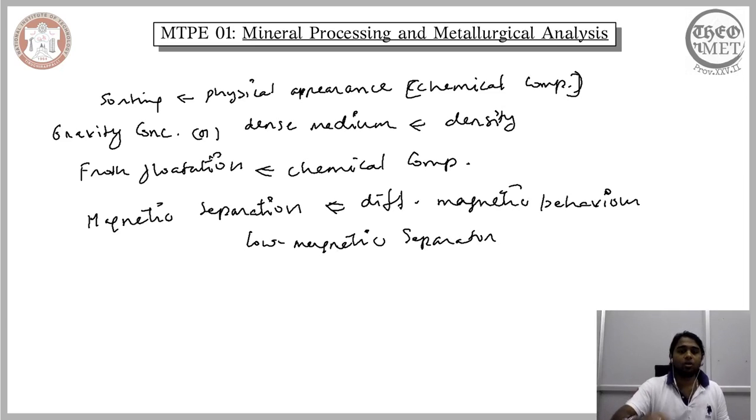And therefore, depending on the degree of response the concentrate gives to a given magnetic environment, the approach that we take also varies. When the desired mineral is highly magnetic, or the undesired gangue is highly magnetic, then all we need to do is expose this mixture of particles to a low magnetic separator, meaning the magnetic field can be low, since the concentrate or the gangue is highly responsive. Despite the low magnetic field, the response will be sufficiently active for the separation.